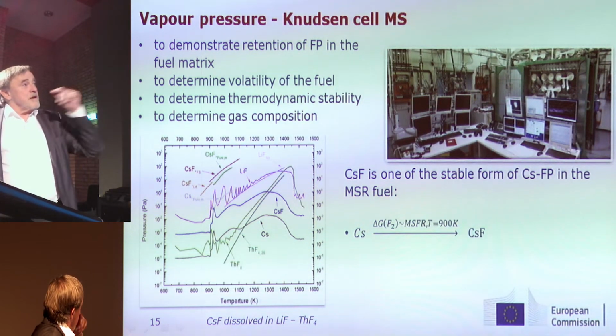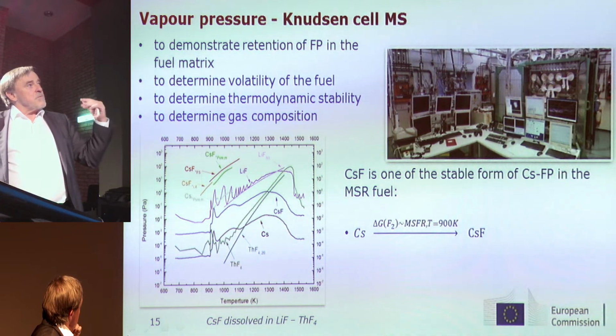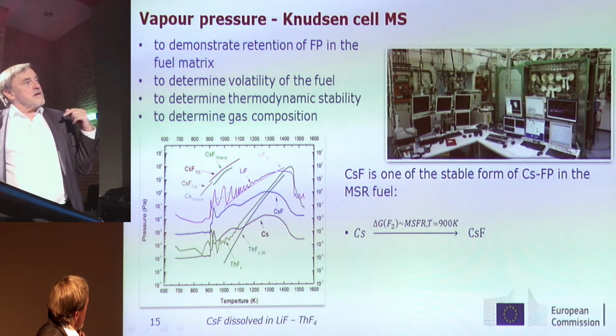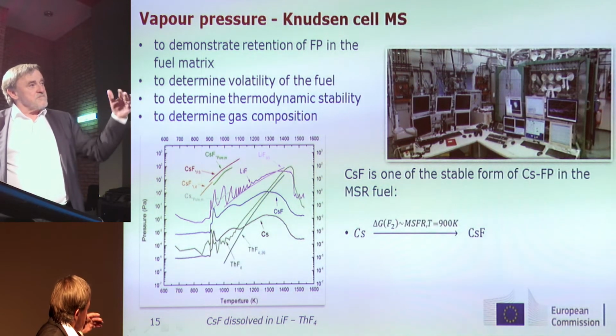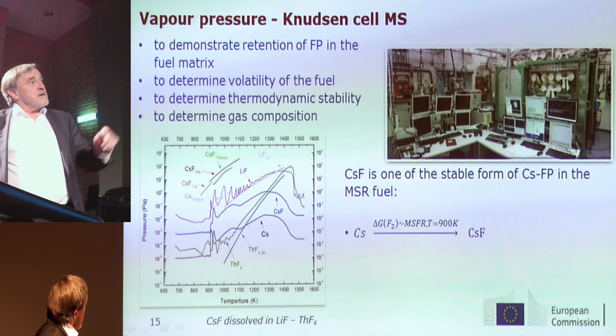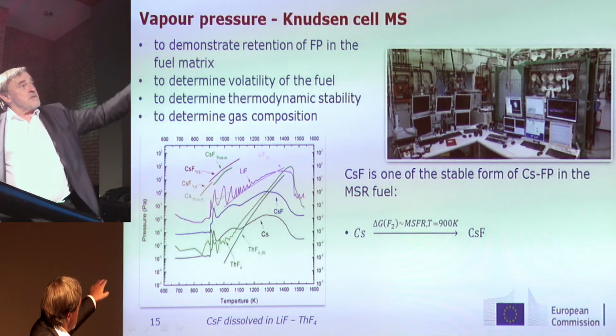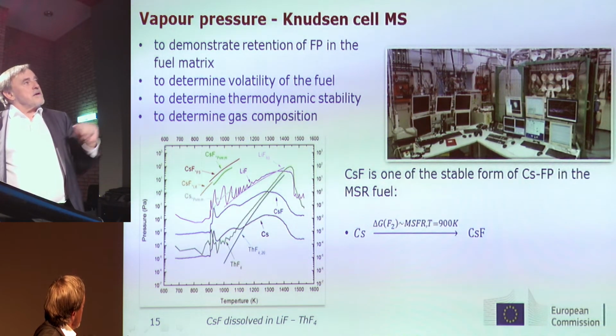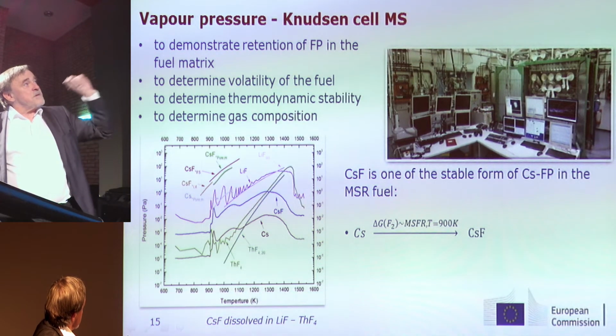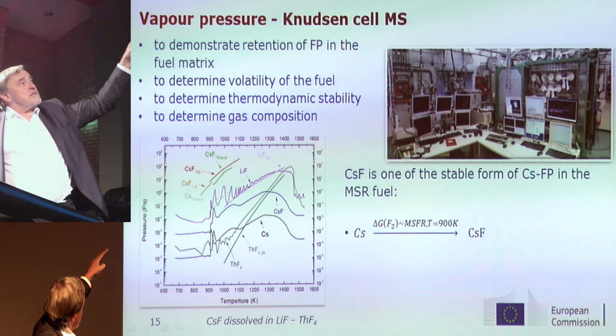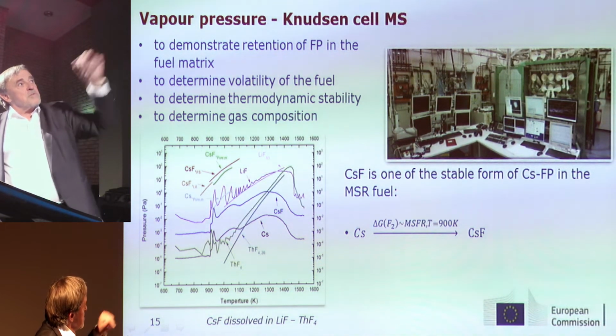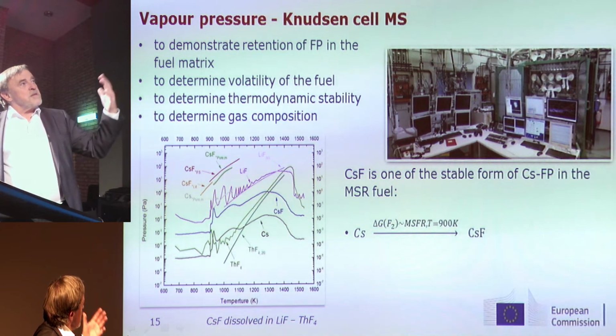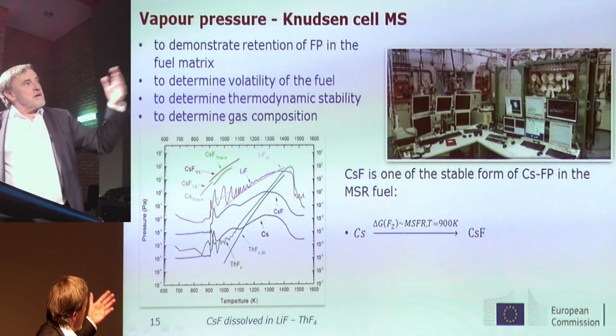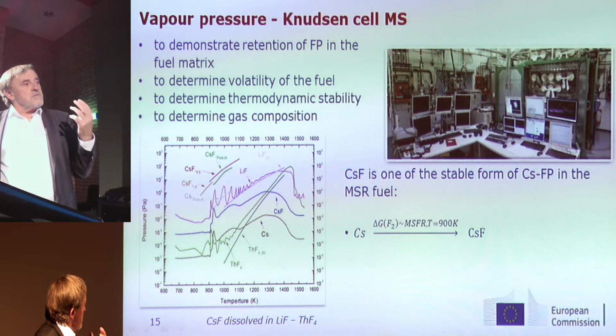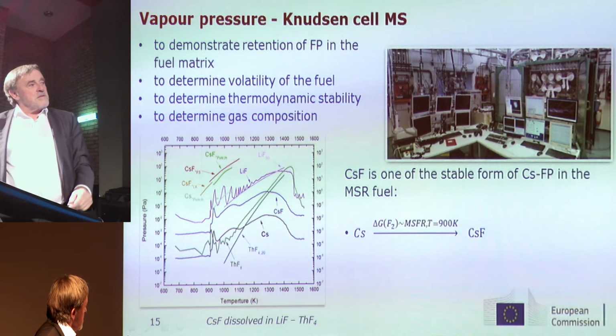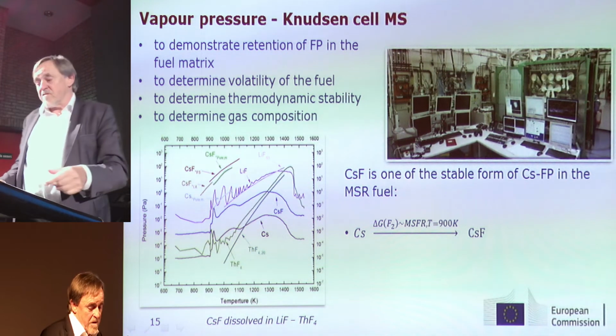So in fact, in the left-hand corner, you see the data that we obtain in the mass spectrometer for these different compounds, and also as a reference, as a function of the temperature which is being applied. We have compared our data for the cesium fluoride, which you see in the middle, the blue line, or the violet purple line, and the data which are taken from the literature partly or have been calculated by ThEC. And we see that these data are essentially much higher than the measurement that we have made with this technique installed in our laboratories, which could be an indication that we have really a complete cesium fluoride. But we believe that this work needs to be continued to have a real final confirmation that we have a complete dissolution of cesium fluoride in this lithium fluoride thorium fluoride mixture.